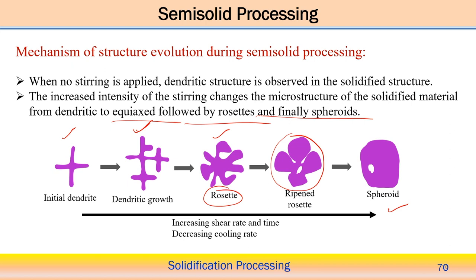because we are basically talking about how the viscosity of this particular material changes. The viscosity gradually decreases with increasing shear rate. The change of shear strain with respect to time is the shear rate. So, this kind of structure you observe with the variation of shear rate and time, and of course, at the same time there is a decrement of the cooling rate gradually along this direction, and we expect the initial dendritic structure to become this kind of spheroid structure. This is the typical mechanism of how the structure forms in semi-solid processing techniques.